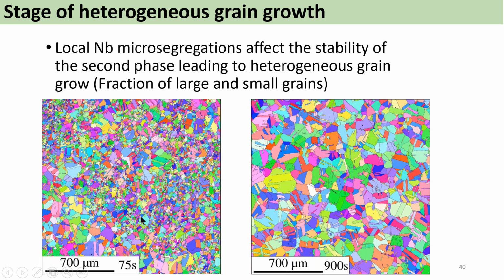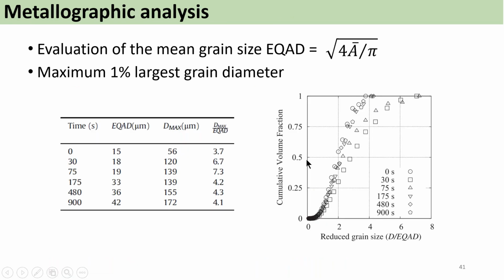It is necessary to wait until the dissolution occurs fully and we have recovered a homogeneous grain size distribution, as you can see here at 900 seconds. And the goal of the Lumet studies was to see: can we use Lumet to know what time we should hold the specimen to reach a homogeneous grain size?